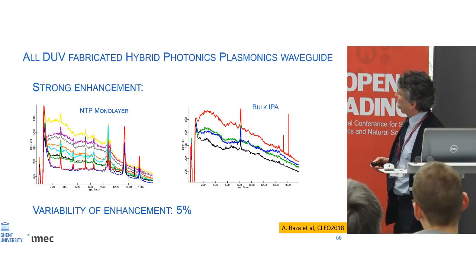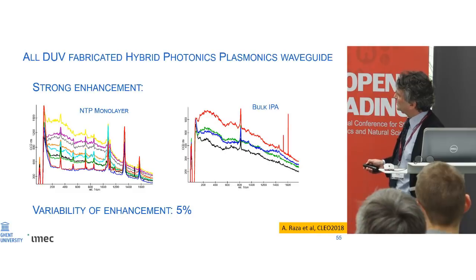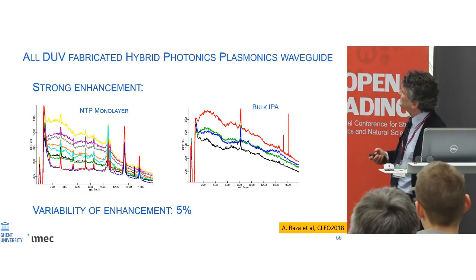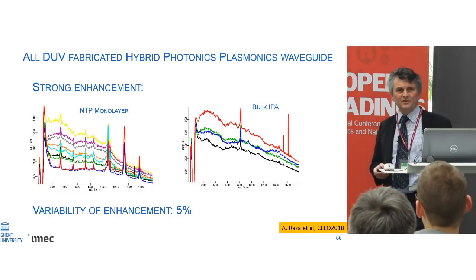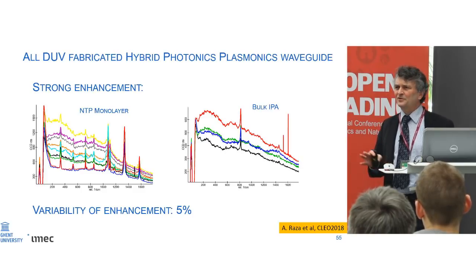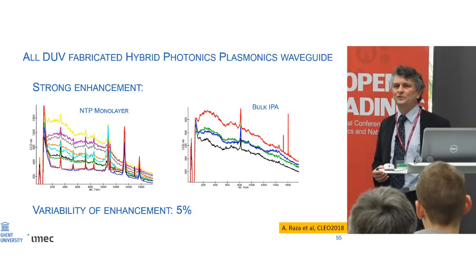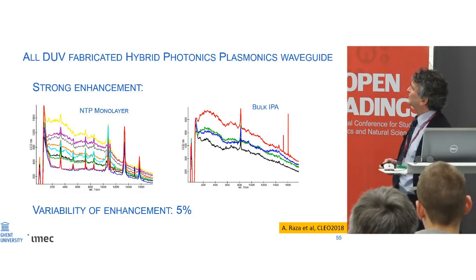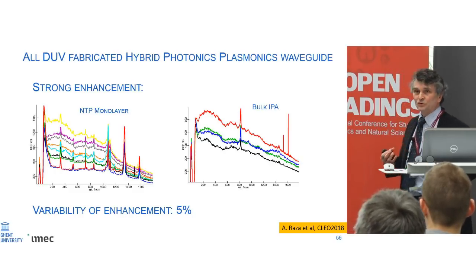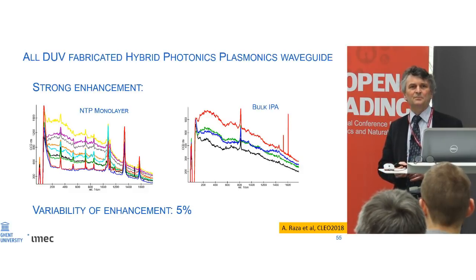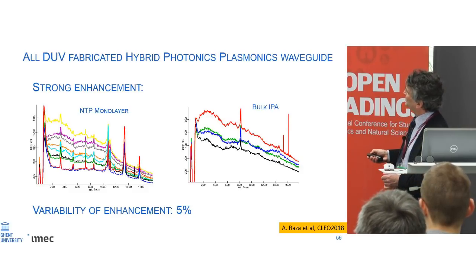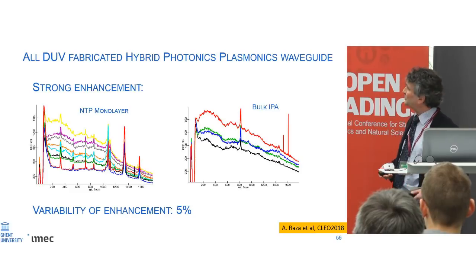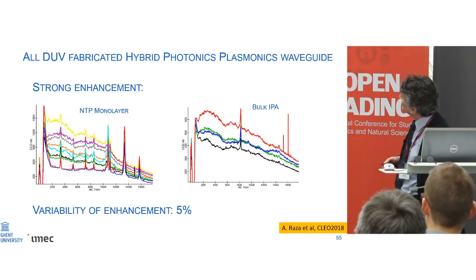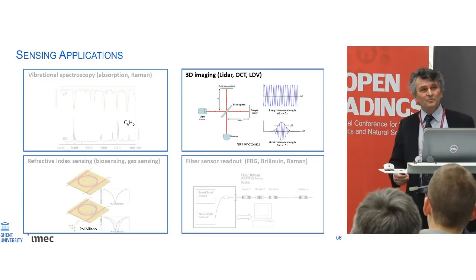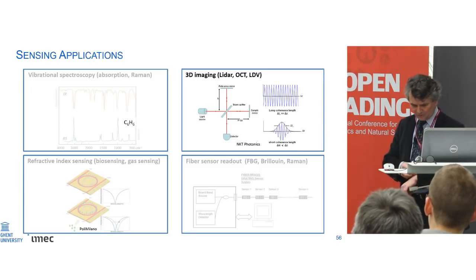So we are quite pleased with this approach, and not unimportantly, the variability of the strength of the signals is within 5%. Plasmonics and SERS always has a bit of a suspicion about reproducibility, certainly if you work with nanoparticles. But in this case, the structures are geometrically rather reproducible, and that means that we also get a rather reproducible result. So that was a few examples of vibrational spectroscopy.